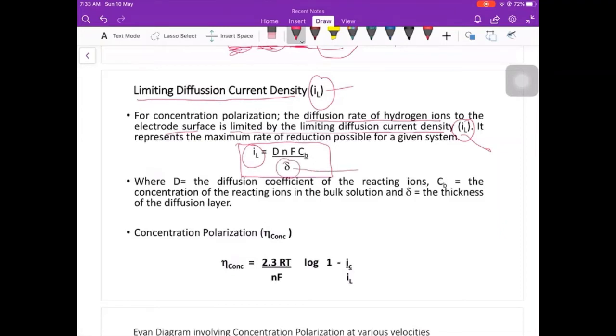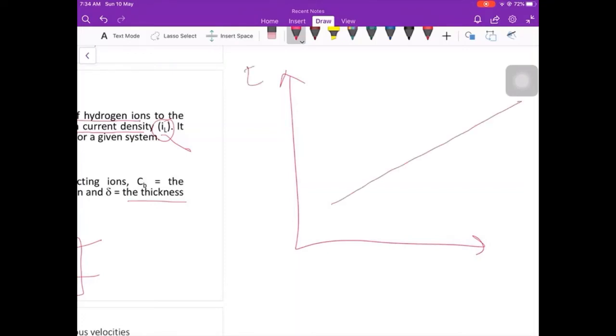So this is the formula involving IL, the limiting current density. Here delta is the thickness of the diffusion layer, D is the diffusion coefficient, n is the number of electrons, F is the Faraday constant, and C is the concentration of active species in the bulk solution. This is the formula of overpotential due to concentration. This is the IC, where it stops, and this is the maximum IL. It only involves the cathodic reaction.